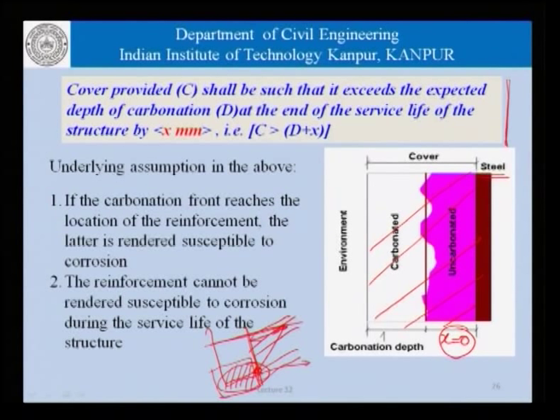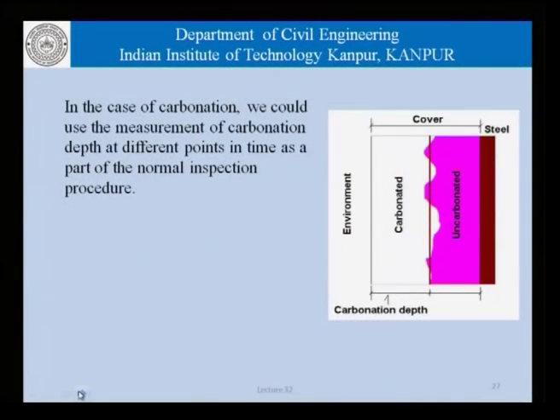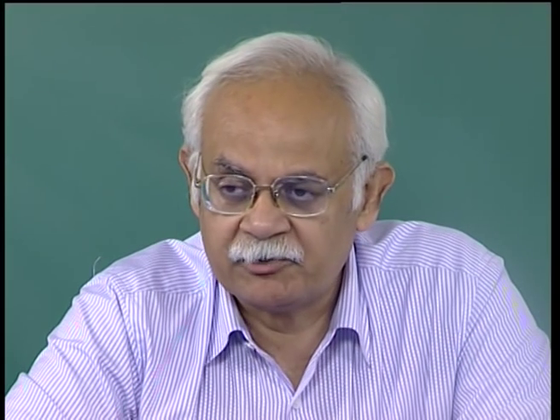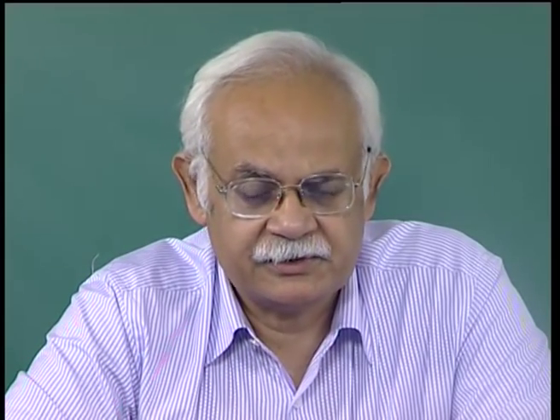Now, continuing our discussion with carbonation, in this case we could in fact use the measurement of the carbonation depth at different points in time as a part of the normal inspection procedure. If we are inspecting a structure, and we normally do that, at least in the case of more important structures, there is a protocol where the structure is normally inspected periodically.